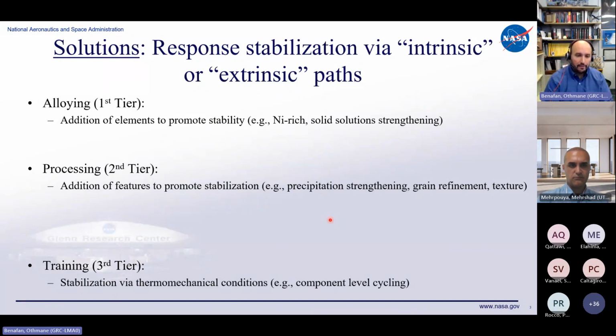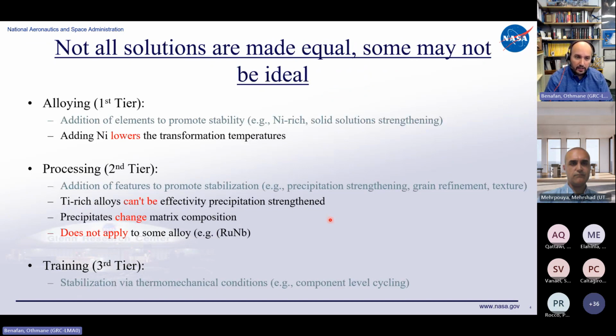The third bullet there is stabilization via thermomechanical conditioning. This could be at the material level, but also at the component level, something that we call training. Sometimes you'll hear the word training used out there, or thermomechanical conditioning, or reconfiguration, or stabilization. There's a ton of different ways to point at the same thing. But here it could be using something like ASTM E3097, which is a uniaxial constant force thermocycling. You can use ASTM E3098, which is a uniaxial thermal free recovery. All those techniques can impart some sort of stability from a thermomechanical perspective. So that's the order of it. But some of these solutions do not always work. And here are some challenges that come with those solutions.